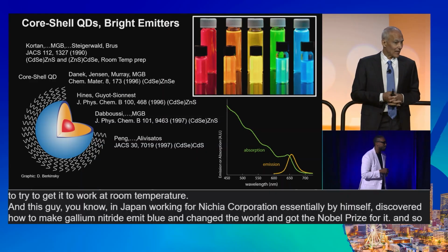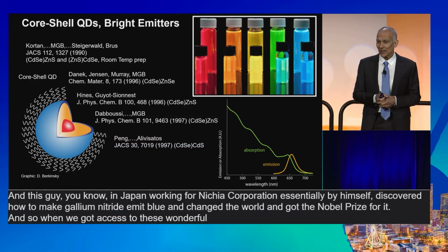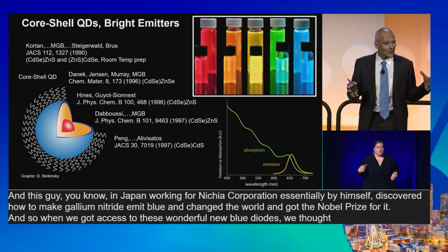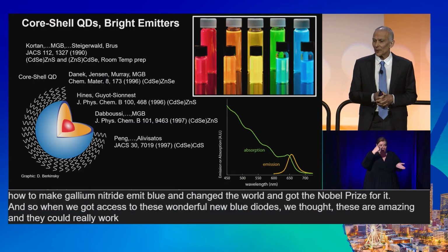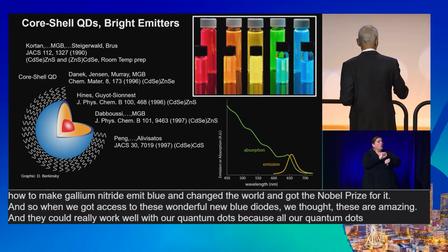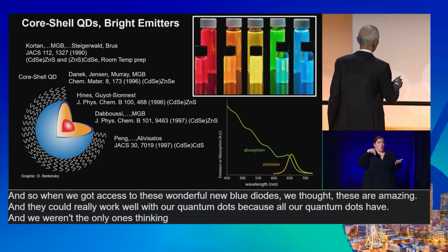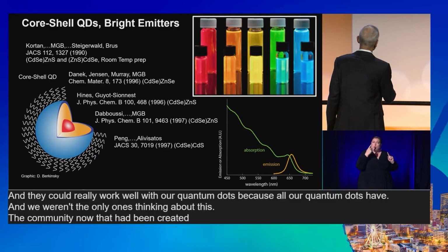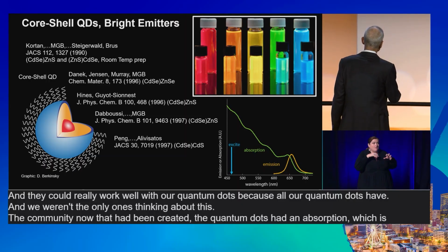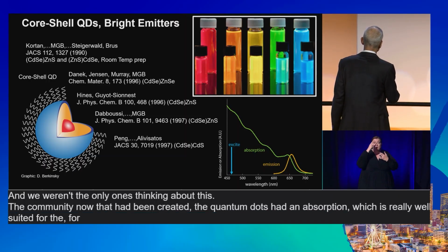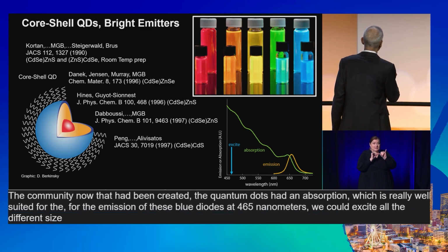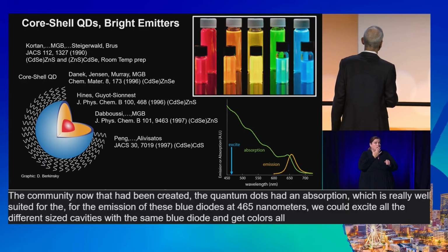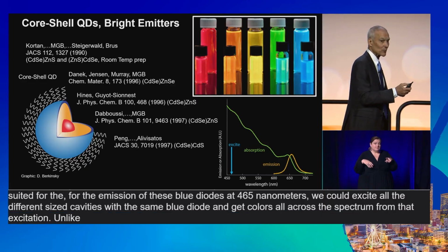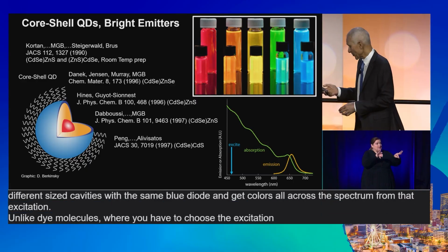And so when we got access to these wonderful new blue diodes, we thought, these are amazing, and they could really work well with our quantum dots. We weren't the only ones thinking about this, the community now that had been created. The quantum dots have an absorption which is really well suited for the emission of these blue diodes at 465 nanometers. We could excite all the different size quantum dots with the same blue diode and get colors all across the spectrum from that excitation, unlike dye molecules where you have to choose the excitation to match the absorption spectrum of the dye.